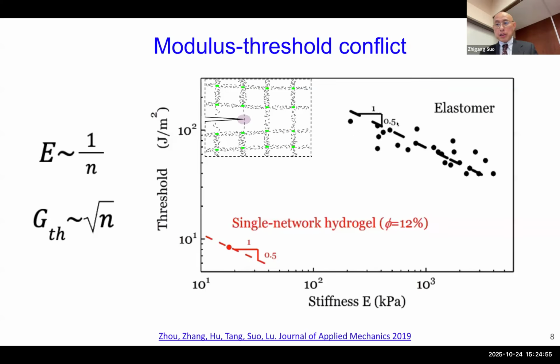So here we plot some experimental data from the literature. Here's the horizontal axis, stiffness, modulus. Modulus scales with the number of repeat units, 1/N. The longer N, the lower E. And the threshold, we just said, scales with the positive square root of N. Longer N, larger G threshold. So the data is negatively correlated. So this is the threshold, that's the stiffness. If you want to have a high threshold, you're going to have a lower modulus.